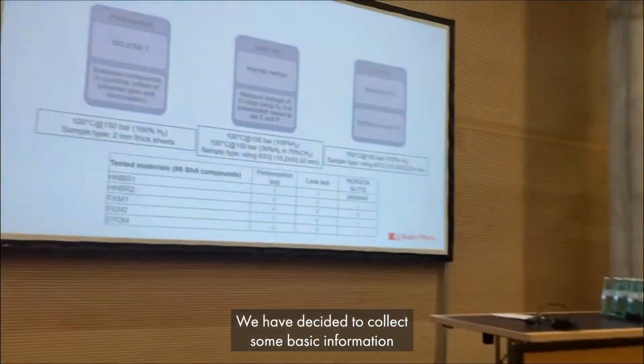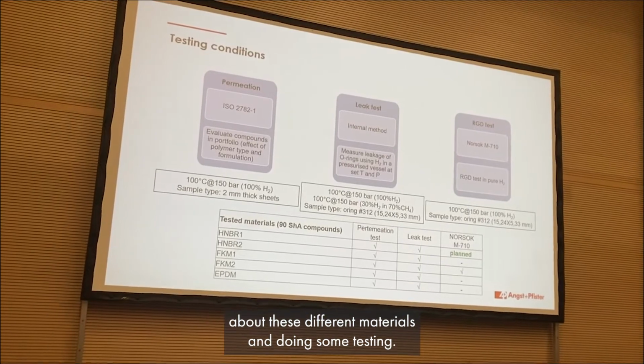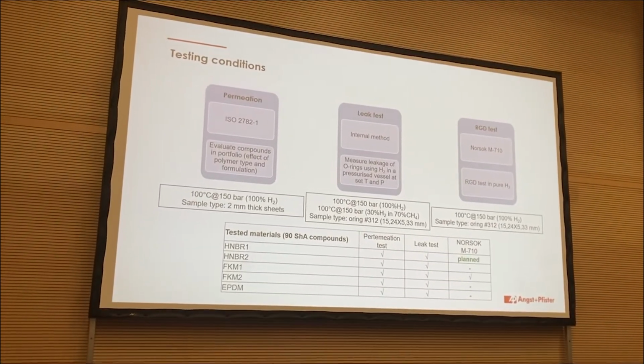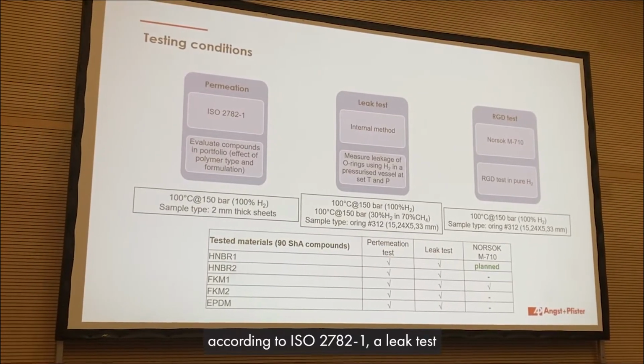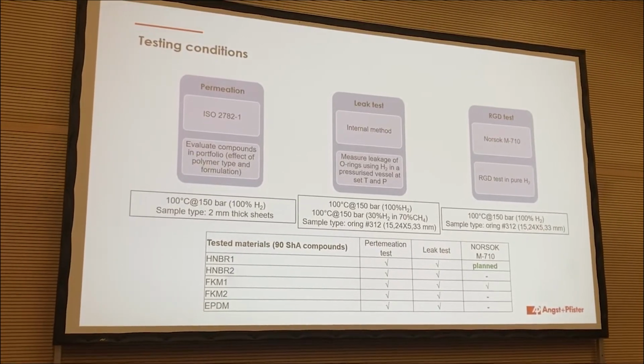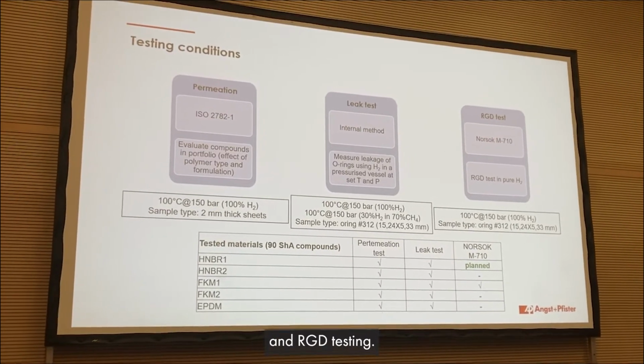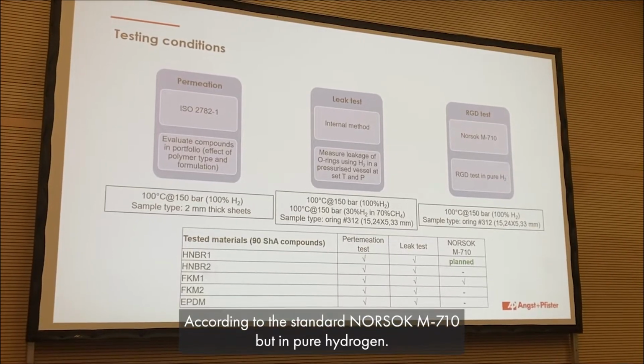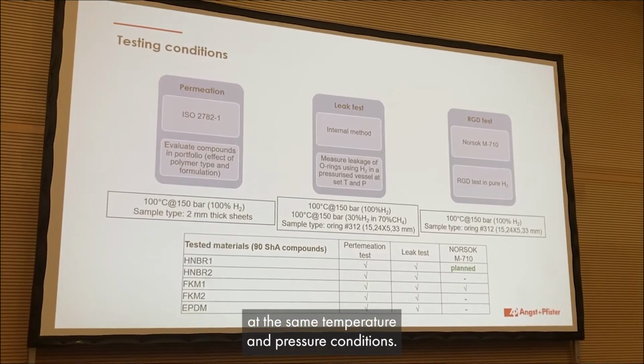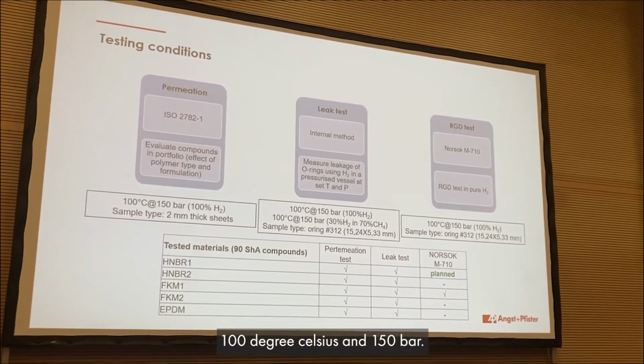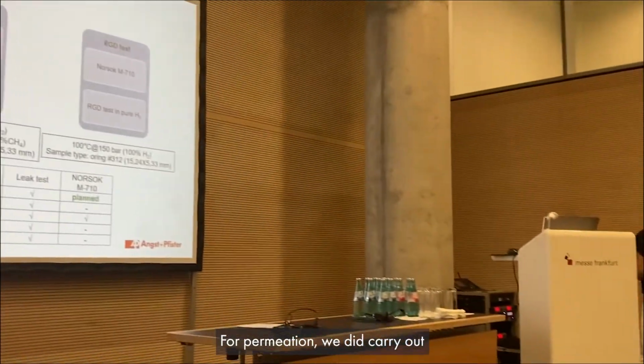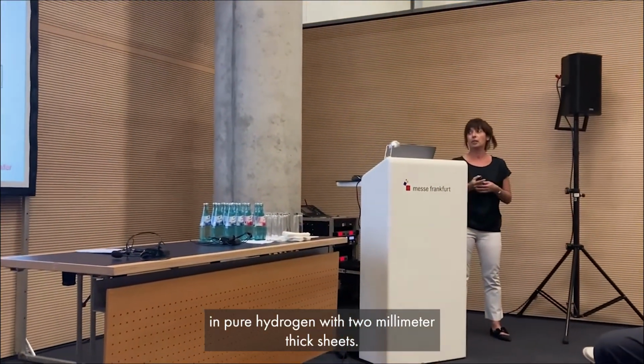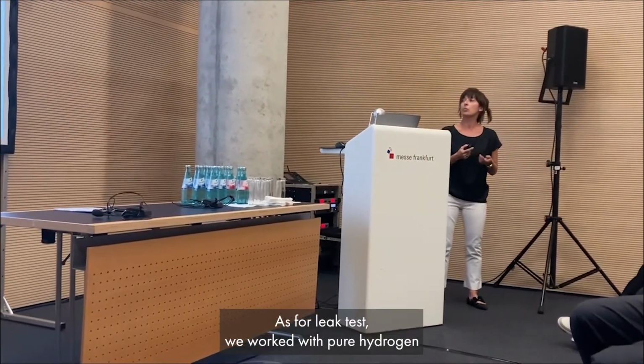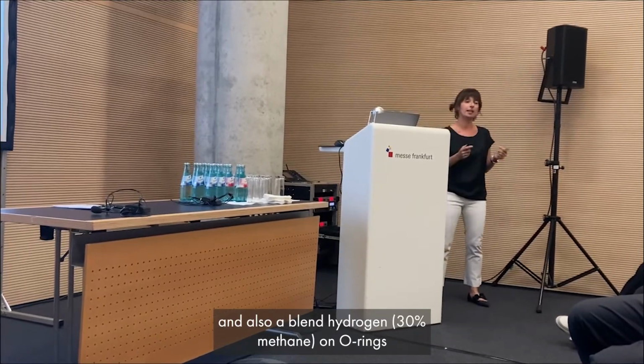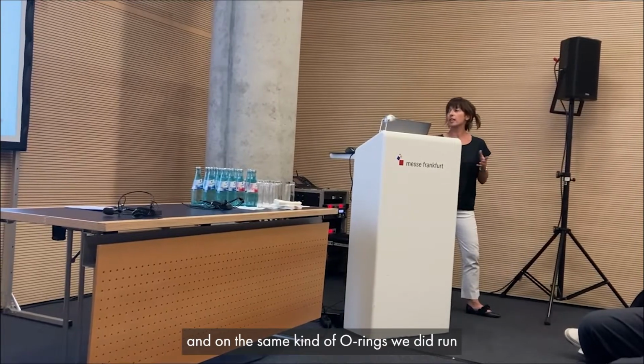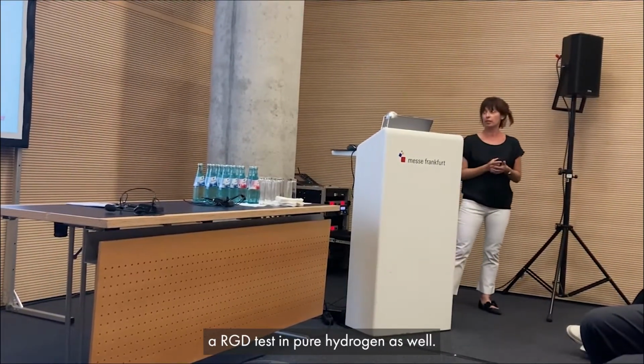What have we done? We have decided to collect some basic information about these different materials, doing some testing. So we carried out permeation testing according to ISO 2782-1, a leak test carried out according to an internal method, and rapid gas decompression testing according to the standard NORSOK M710, but in pure hydrogen. In all the cases, we did work at the same temperature and pressure conditions, 100 degrees C at 150 bar. For permeation, we did carry out permeation tests in pure hydrogen with 2 millimeter thick sheets. As for leak test, we did work with pure hydrogen and also a blend of 30% hydrogen in methane on O-rings. And on the same kind of O-rings, we did run rapid gas decompression test in pure hydrogen as well.